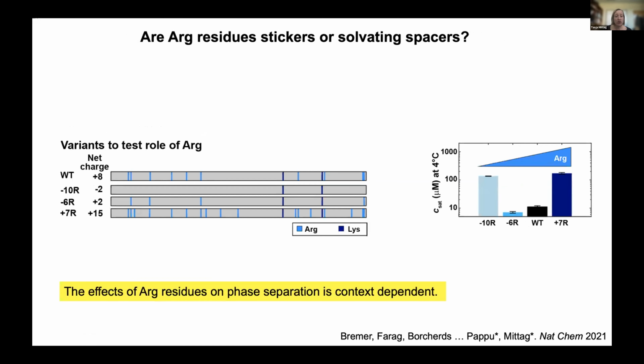Then she looked at arginine residues and showed that when adding 7 arginine residues to the intrinsic 10 arginine residues of the wild type, it weakened phase separation, seen here as the higher saturation concentration, of course. So you needed more protein for phase separation. When removing 6 of the 10 arginine residues, it strengthened phase separation. And both of these data points would suggest that arginines may also be highly solvated spacers.